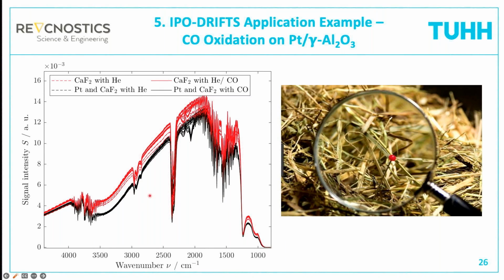We have some bands here where we normally have the CH vibrations. I still don't know where this comes from. I think maybe someone touched the mirrors or so. There's a fingerprint. There should be no CH vibrations in CO oxidation. Then we have here the gas phase CO, this butterfly here, and this is actually the needle. This is our adsorbed CO on the platinum surface.